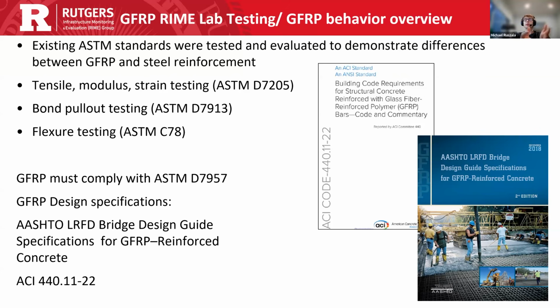There's also a large amount of durability testing, which was a little bit out of scope for our lab. So some of those tests are the tensile testing of the GFRP bar itself. So that's tensile modulus and strain testing, as well as bond pull-out testing, which we specifically use NJDOT HPC for the bond pull-out testing, as well as a flexure testing to get an as accurate overview.